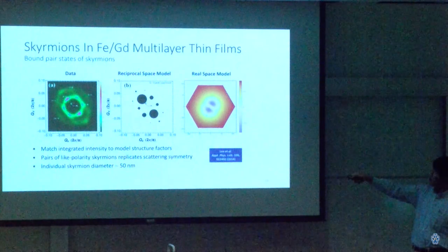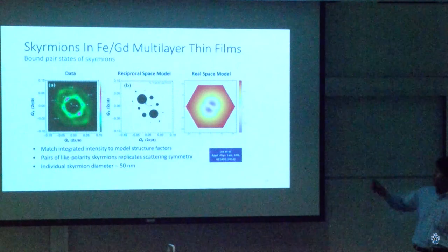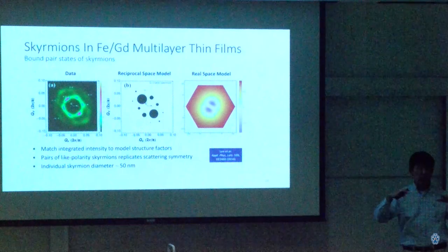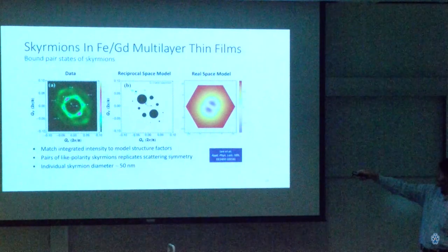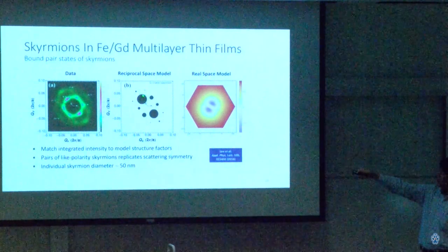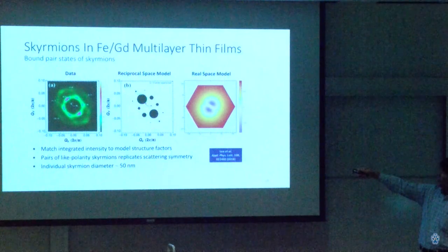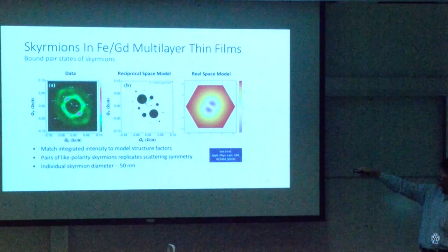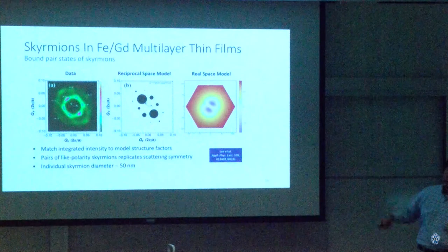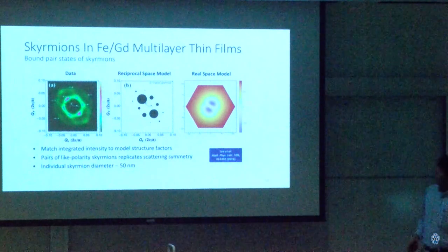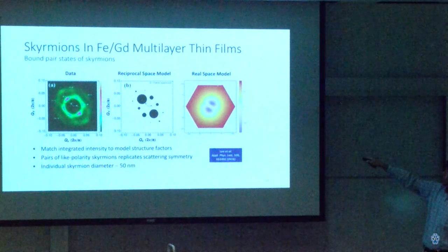So what we did was we took our data, we found how many X-ray counts were under each peak, and that's what the diameters represent here. Instead of seeing actual data, we have circles with diameters proportional to the number of X-ray counts in the peak. And then we tried to model this